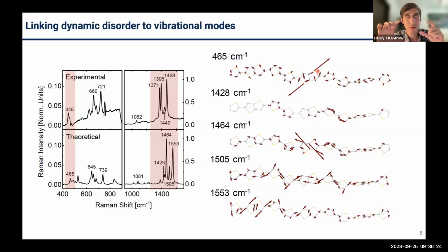And this, we contextualize in the context of the typical fluctuations of hairy rod polymers, in that typically in a liquid crystalline system you form a very low entropy system due to the side chains locking in the backbone. As a way to increase entropy, these systems often undergo segmental twisting motions, which is what we see from correlating the frequency of this mode to the structural motions of this mode as well. So this gives more insight into the structural parameters that are driving this dynamic disorder.